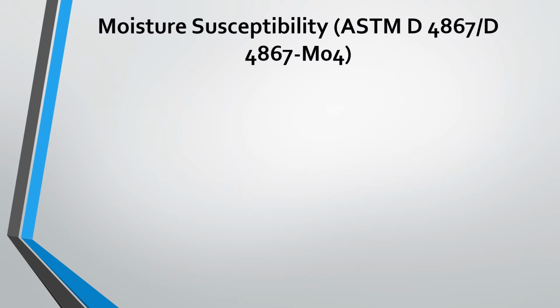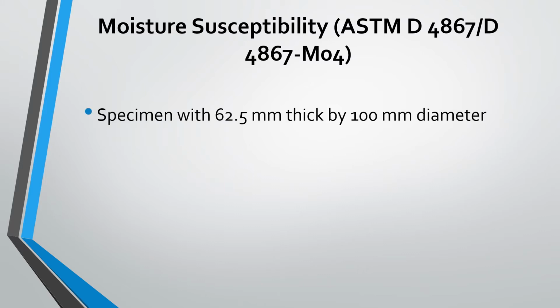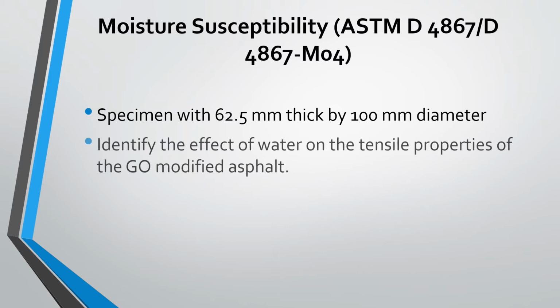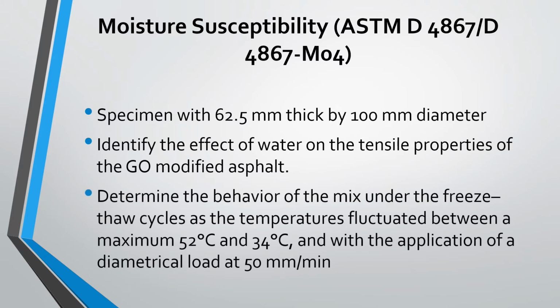The moisture susceptibility of GO-modified asphalt will be assessed using ASTM D4867. The specimen with 62.5 mm thickness by 100 mm diameter will be used. It will identify the effect of water on the tensile properties of GO-modified asphalt. It will determine the behavior of the mix under the freeze-thaw cycle as the temperature fluctuates between the maximum of 52 degrees Celsius and 34 degrees Celsius, and with the application of diametrical load at 50 mm per minute.